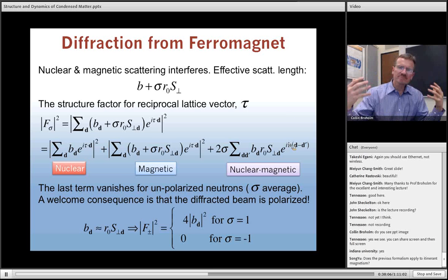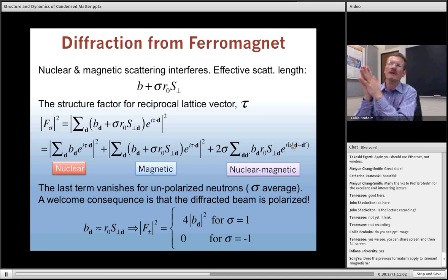And so the fact that we're dealing instead with a system where the electrons are itinerant is tough to get a really strong experimental signature of. It doesn't show up in this form factor very well, even though conceptually you would expect it to eventually show up at sufficiently small, so I should say different, a sufficiently short momentum transfer, which corresponds to large distances in real space. I ought to see some sort of effect of the itineracy of those electrons.